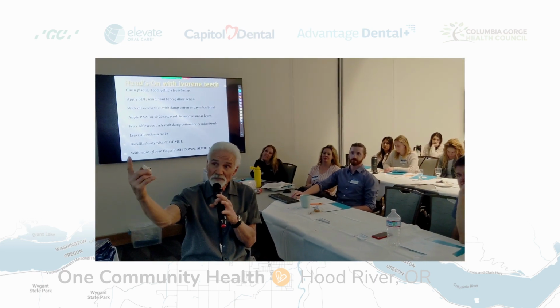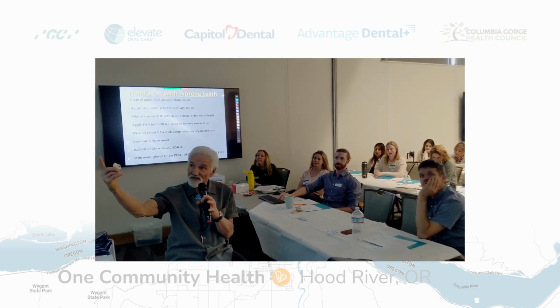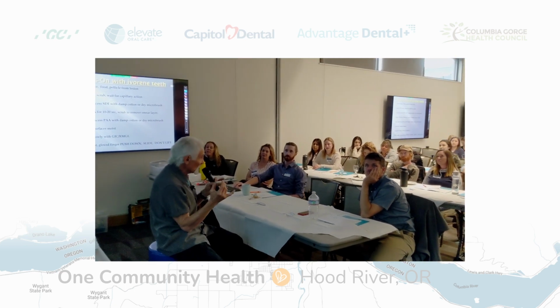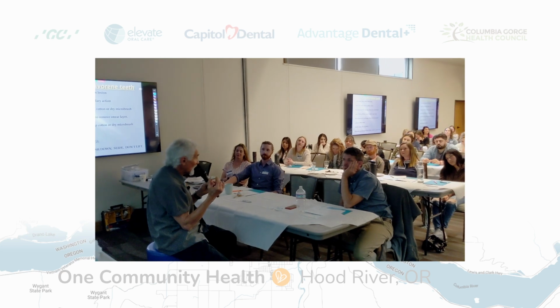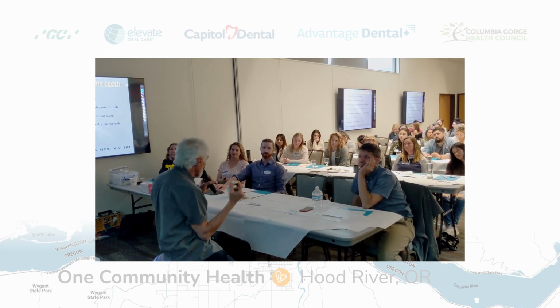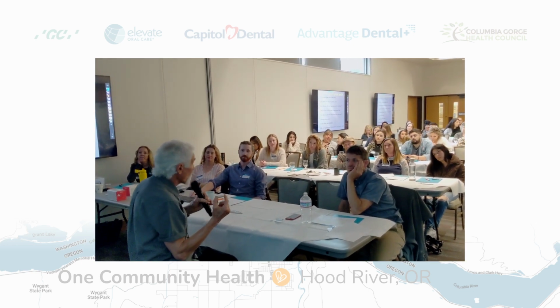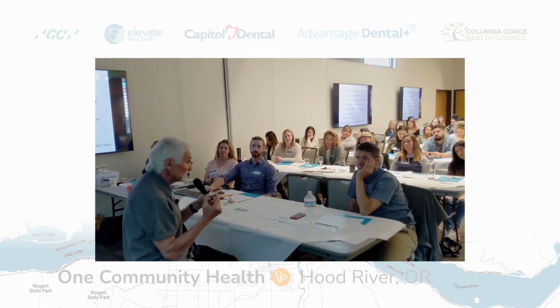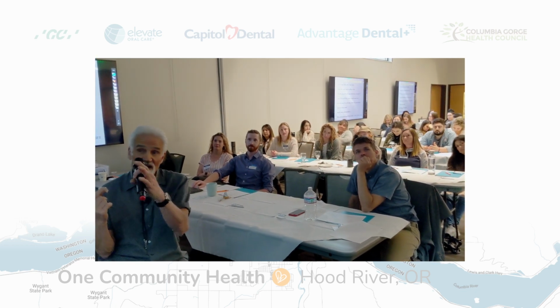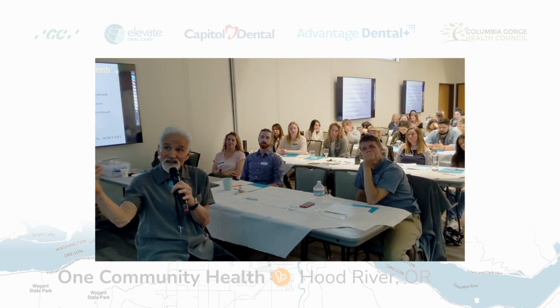And what we're going to do is you're going to apply polyacrylic acid for 20 seconds. Then you're going to scrub to remove the smear layer, because the smear layer forms through the decay process. You've heard of the smear layer forming when you use a drill. Well, guess what? Decay is like a drill, and it forms a smear layer also. And you have to remove that for the glass ionomer to be able to adhere. Okay, then you're going to wick off your excess polyacrylic acid with damp cotton or a dry microbrush.